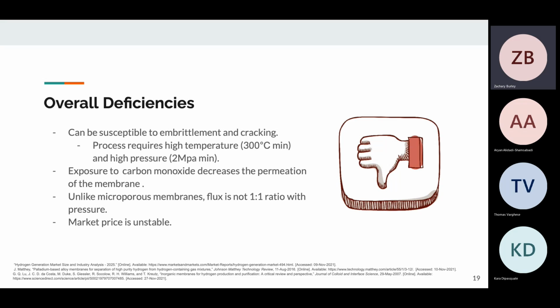Palladium-based membranes have some deficiencies as well. Firstly, when used for the application of hydrogen separation specifically, the membrane's exposure to carbon monoxide causes the permeation of hydrogen to decrease with continued use. This problem can be resolved, but only by increasing the overall operating temperature of the system. The minimum recommended temperature for the separation of hydrogen is around 300 degrees Celsius. And as can be seen from the P&ID, we implemented an operating temperature of around 550 degrees Celsius.